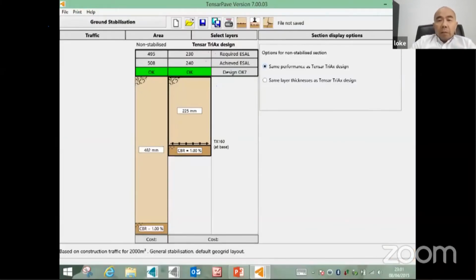Now, how do we do this? You can do this manually, or we incorporate it into computer software to help us do it faster. So you can see that without geogrids, you can have a 482 millimeter thickness. Look at the number of ESAL again. Okay, so you can see that the achieved ESAL is much better, and this is at 225 millimeters of thickness. So you are reducing the thickness by more than half, in terms of using a geogrid.